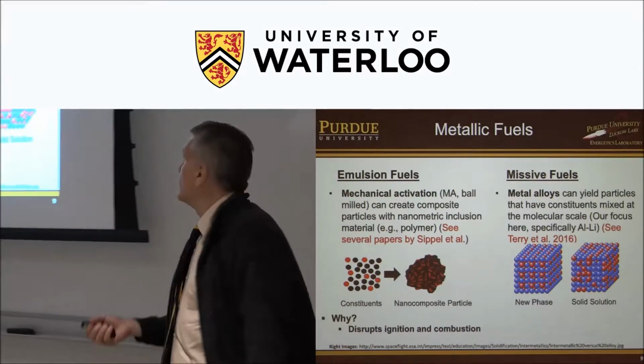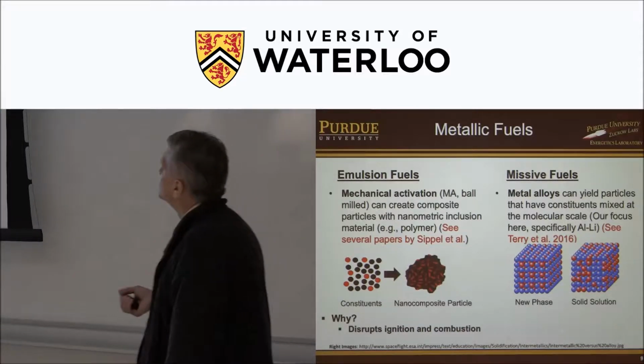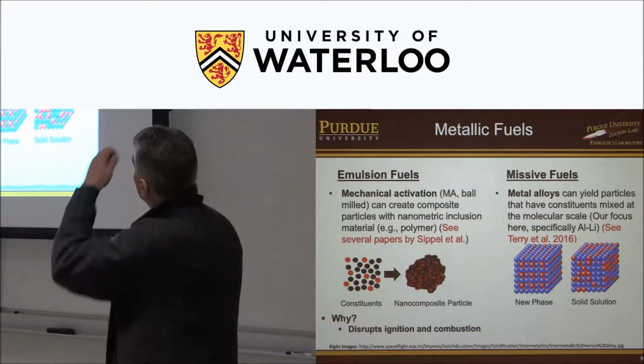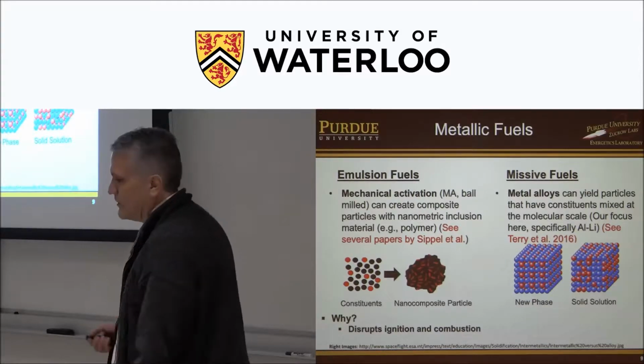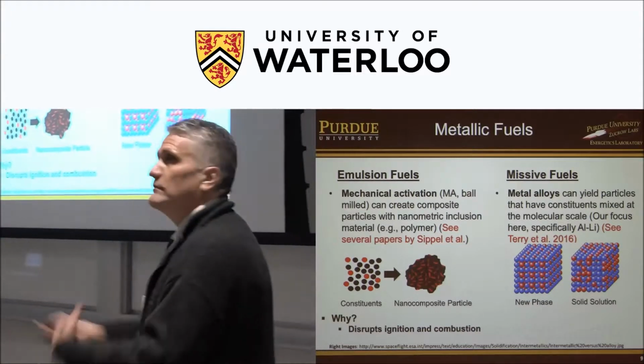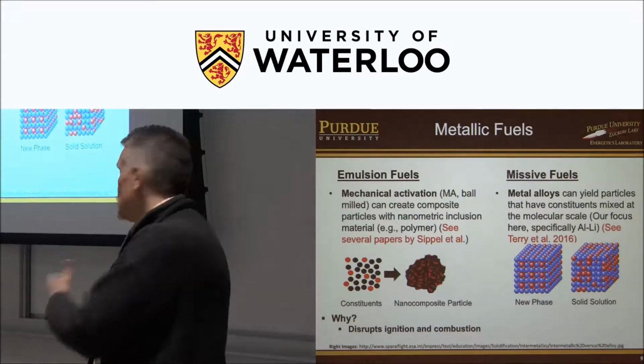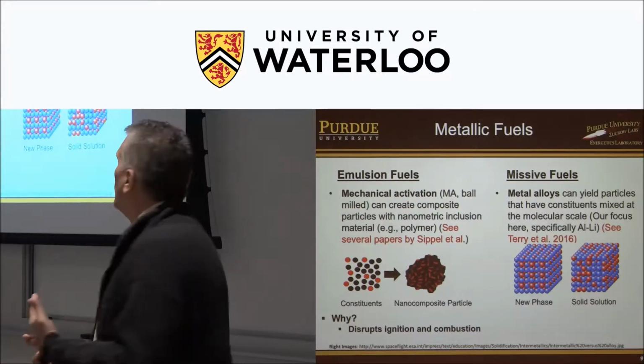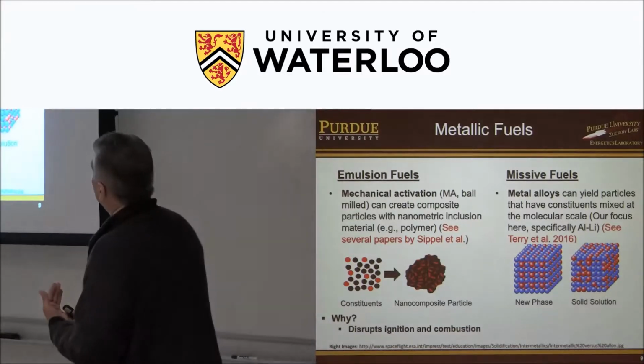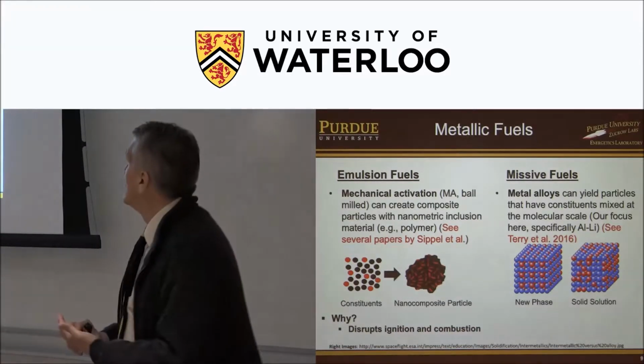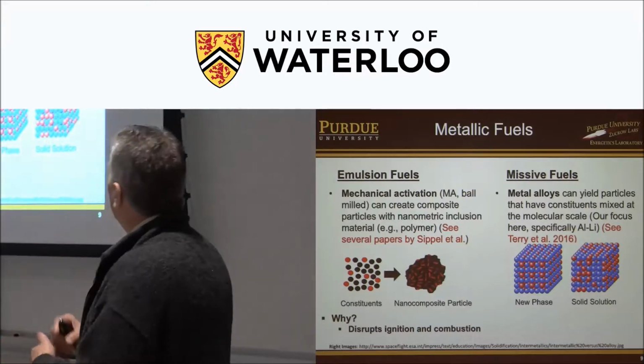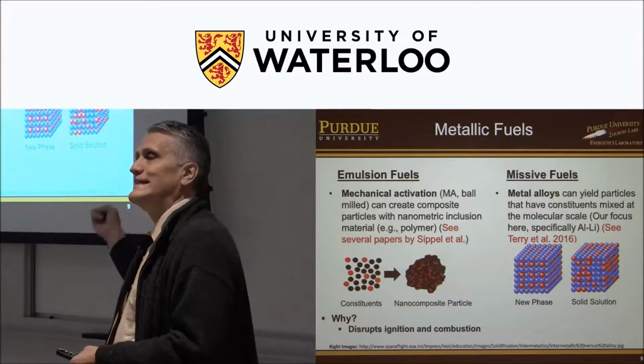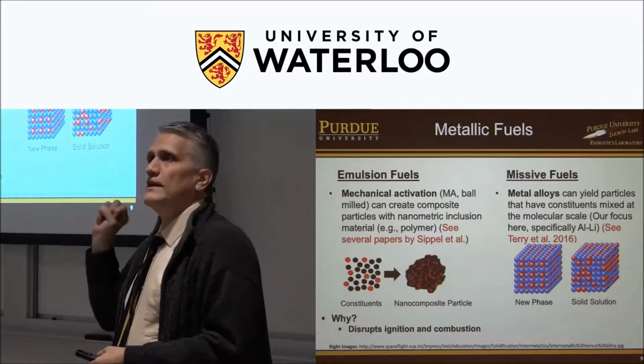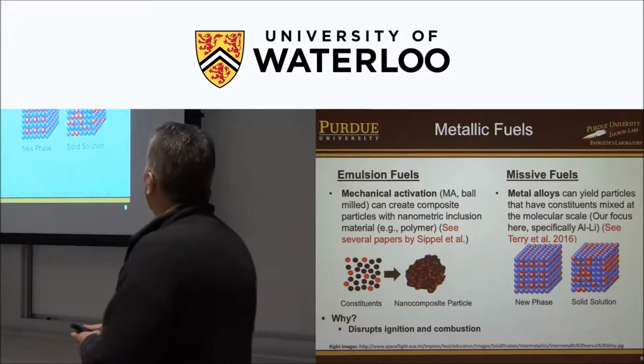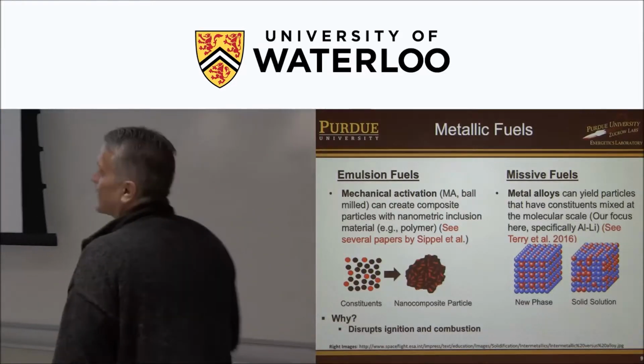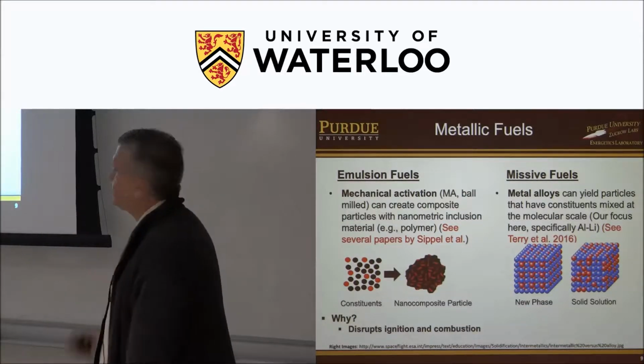Alloys are an analogy to emissive liquid fuels. And so we've looked at, in particular, this aluminum-lithium. We also looked at other alloys. But for this one, the thermochemistry says, okay, look, this could be good for both cutting the HCl emission as well as performance. And I'll show that it also has the properties, because lithium is much more volatile, with a lower boiling point. It can micro-explode the particles into smaller droplets, and that can, very importantly, improve performance.